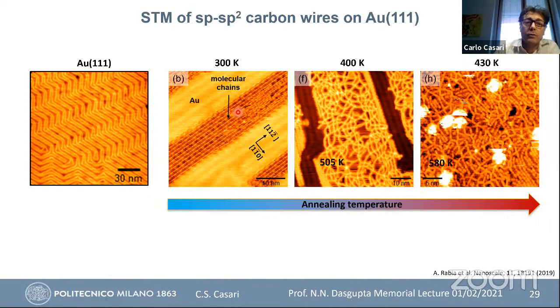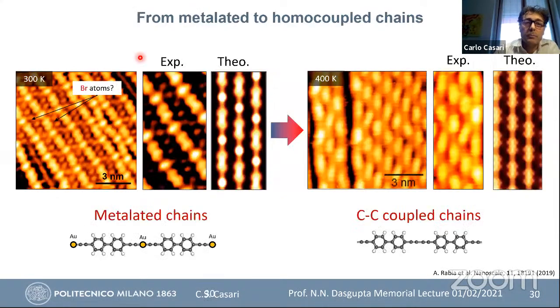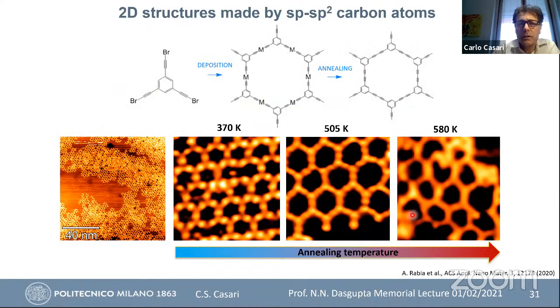And here we follow this because at low temperature, I mean room temperature, we see the gold in between the chains, and this is theory. By increasing the temperature, it is not very clear, but the bright protrusion here is absent, and this is the theoretical prediction. So we move from these metal organic chains to all carbon chains.